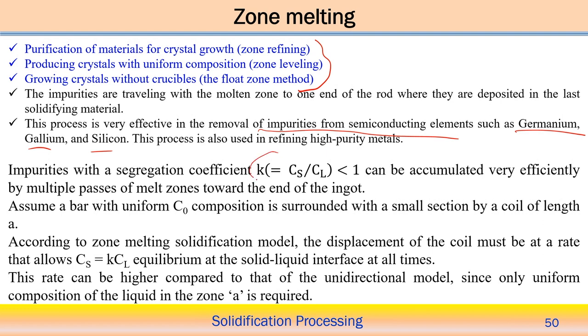And here we are missing this particular point, the segregation coefficient k less than 1 in this case. You can treat it like that. If you remember the temperature versus composition plot in a binary alloy system, here is the melting point of A, which is 100% A, and this side is element B. So, it is a binary alloy, and the slope is this way. When this is the slope, then definitely the melting point of pure B is less than the melting point of pure A. That is why, in this situation, the segregation coefficient will always be lower. So, in this case k should always be less than 1.